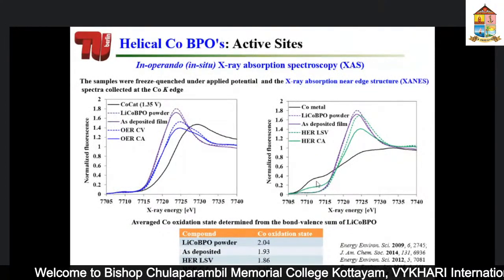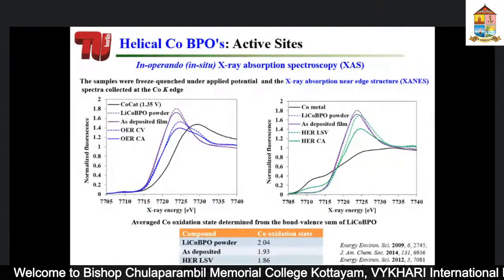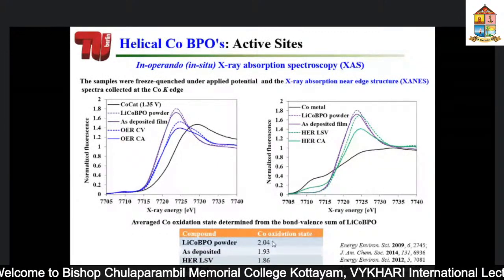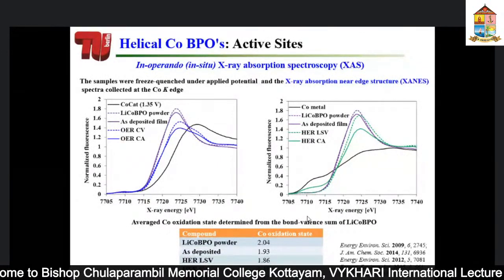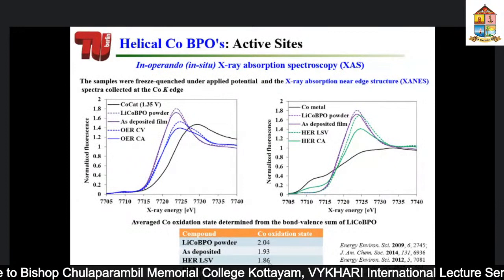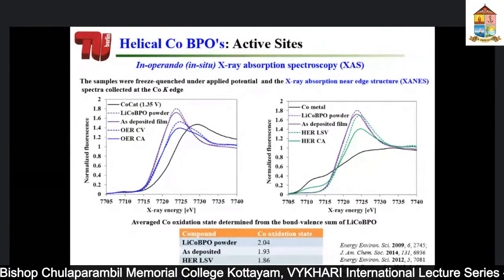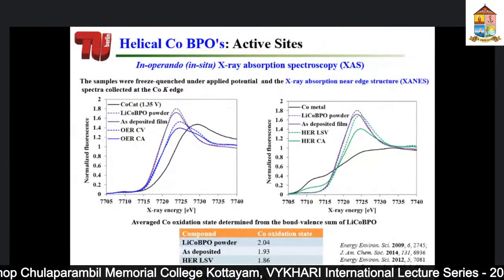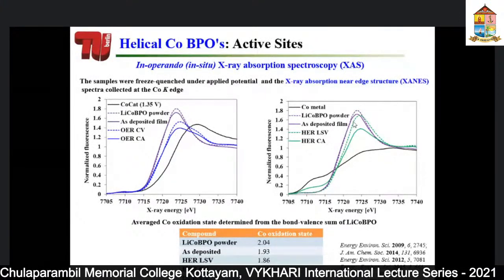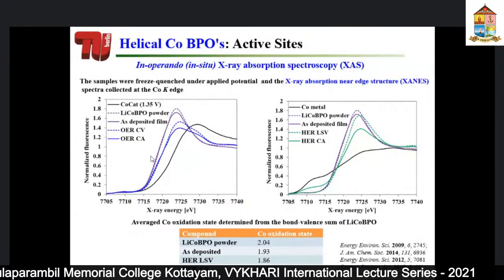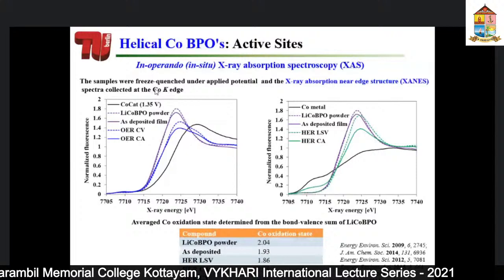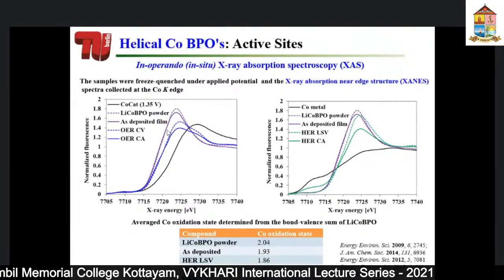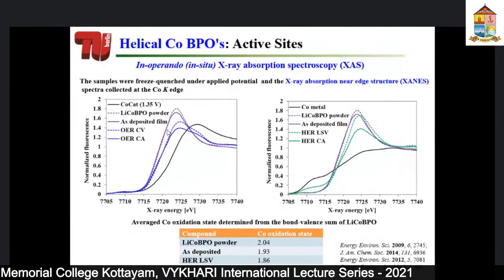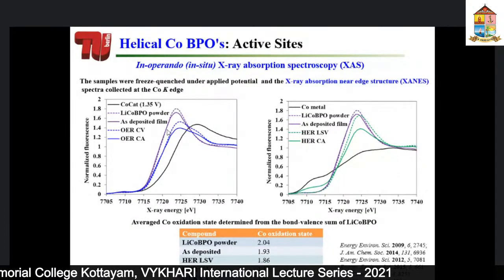Similarly, in the hydrogen evolution case, you had your oxidation state +2, and then after your catalysis, you decreased your oxidation state to 1.86. That means the cobalt you had in your material got reduced, and here the cobalt is oxidized. This is done for the cobalt K edge, so we can only get information on the cobalt sites.